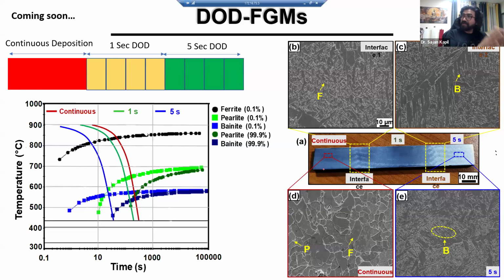This is monolithic material, a single material, but just by tweaking that path, I'm able to control the microstructure. Here you see this portion is rich with the conventional microstructure. When you deposit mild steel by 3D printing, typically you see pearlite and ferrite. But if you do some tweaking with the path planning, you see this region is rich with bainite. And this is only mild steel, because again, like I said, I need more material experts to discuss. If they have some ideas, like, can you vary the microstructure in this particular alloy, we can try, we can work it out.